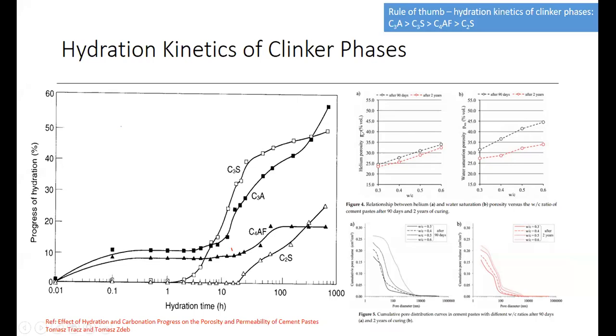Here I have utilized some results taken from a helium porosity meter and the water saturation porosity with the water-cement ratios. You can see the red line is after 2 years, and the black line is after 90 days. You can see it's reducing. The porosity is getting reduced with time. It's basically because these reactions can happen over a longer period, and with time the porosity will be reduced. That is the mechanism.